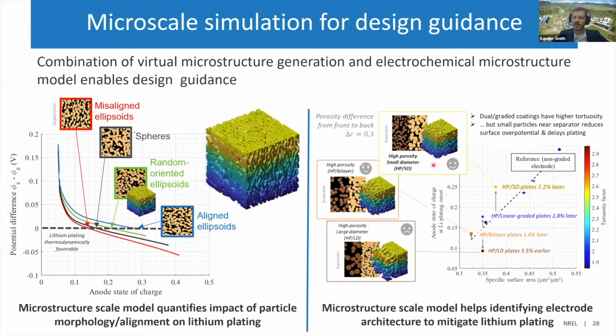I should mention that a practical consideration, you don't want to go too high in surface area for a real electrode, because the surface area scales with the rate of side reactions. And so your SEI consumption of lithium ions, for example, is going to double if you have double the surface area. So this is a good way of trading off both big particles and small particles, as well as different porosities.